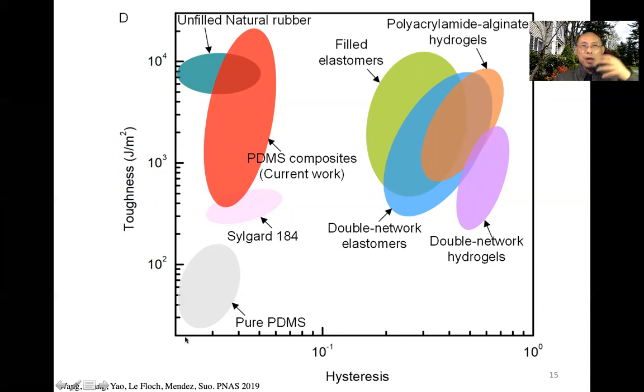Now, among elastomers and hydrogels, unfilled natural rubber actually fulfills this behavior. The hysteresis, at least for 20, 30% of stretch, actually all the way to 100% stretch, is quite small, less than 10%. But for all these other materials, including our tough hydrogel, the hysteresis, as I showed you, is enormous, and toughness is enormous. Now, for our composite, we use two versions of PDMS, a stiff PDMS and a soft PDMS. With this composite, we can easily achieve toughness as high as natural rubber.